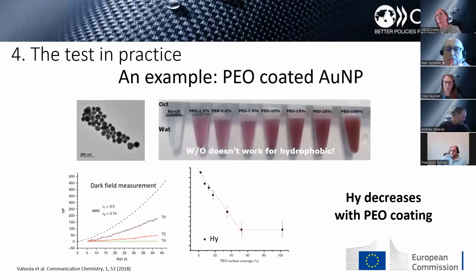But thanks to our method based on dark field microscopy, which allows us to measure the binding affinity of our material on 3 different collectors, we were able to determine the value of the hydrophobicity index of gold nanoparticles without the PEO coating, which are very hydrophobic, as you can see from the graph.